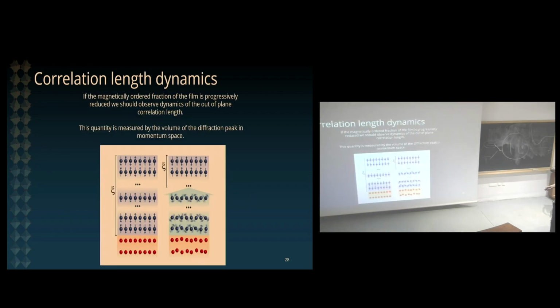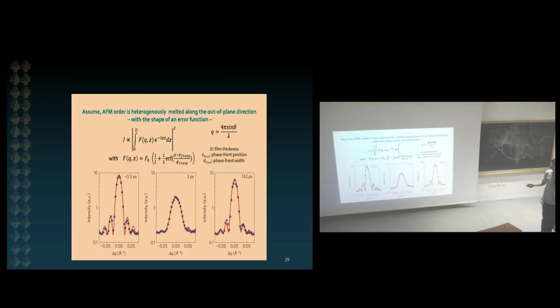So the idea of the experiment is very simple. If we excite the lattice of the substrate and we induce some variation in the properties of the antiferromagnetic order in the thin film, there is an interesting scenario in which, by exciting a strain wave here, we start to excite first the few layers at the interface, and then this will generate a propagating excitation across the film. And the idea of the experiment was to probe the volume of the scattering response in momentum space. Many of you do thin films. So you do X-ray scattering, and you're used to looking at finite size oscillations around the Bragg peaks of the film. This is the same idea. So let's look at the finite size oscillations, how they vary over time when we do the excitation. And that's what we observe in the experiment.